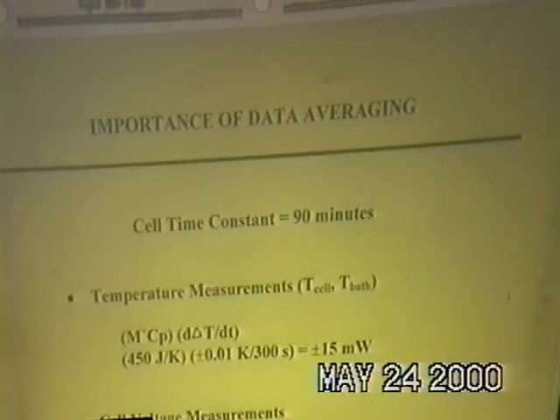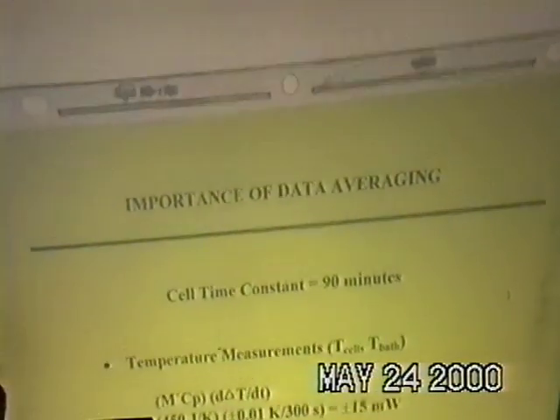Your cell voltage measures vary due to gas bubbles, and you may have between two measurements plus or minus 2/100ths of a volt. If you're running at 500 milliamps, that's an error of plus or minus 10 milliwatts. But if you average data, these errors are removed because your cell is averaging all the time. It's averaging everything that's going into it over a long time period. So because the cell is averaging the effects on it, you should average measurements that you make, and perhaps also measure the temperature to a thousandth of a degree, for example. That would help also, which we did in the data we had in Japan.